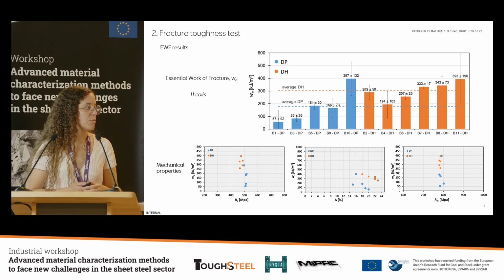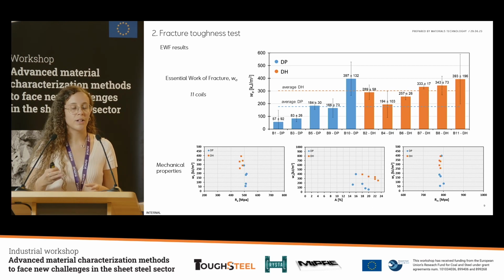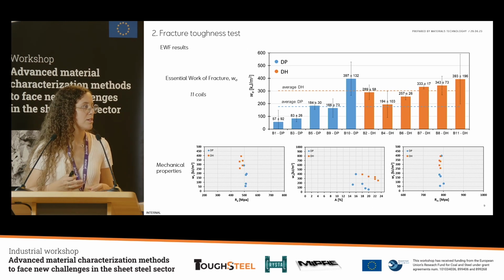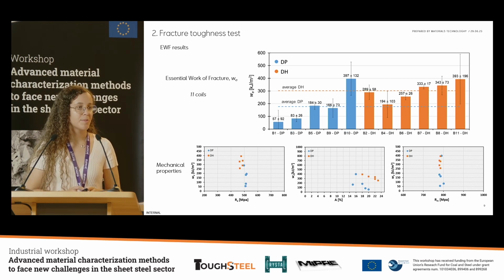Also with the maximum resistance, we found the same, that the values were similar for all the coils. However, for the essential work of fracture, it was better in the DH materials. Finally, we wanted to simplify this process even more.